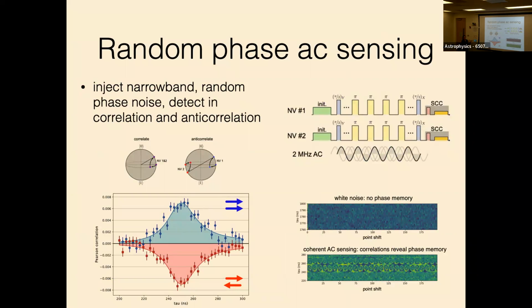And then we can just do a really simple thing, which is prepare the NV centers on opposite sides of the Bloch sphere and look for anti-correlations. And we see this beautiful anti-correlation. And the interesting thing is we actually figured out that our signal generator was supposed to have no phase memory when you programmed it in a certain way, and it totally had phase memory.